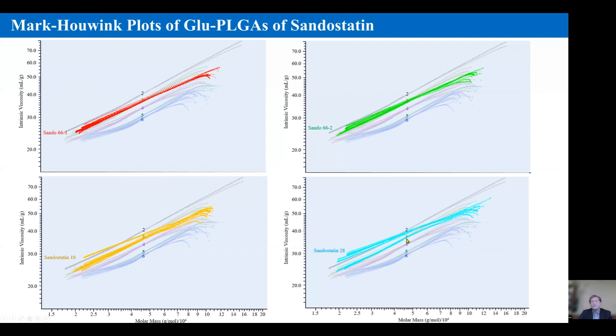But the main point is that as the molecular weight is lower, you have a branching number of about 2 and 3. As the molecular weight increases, the branching number increases up to 4, and sometimes, in a very rare case, up to 5, but usually about 3 and 4. So this is how we characterize the molecular weight.